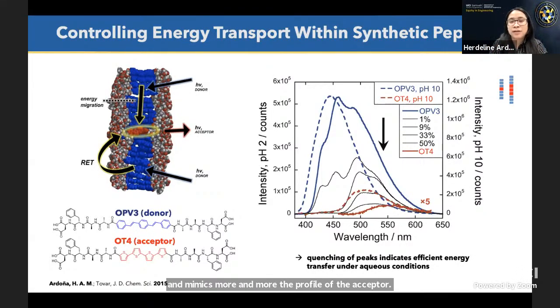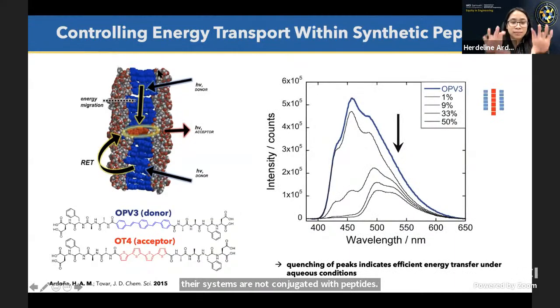What I want you to take away from this graph is that we were able to see this quenching of peaks, which represents a successful energy transfer even under completely aqueous environments, which usually does not happen easily when these electroactive systems are not conjugated with peptides. As a control, we looked at just assembling the donor stacks and acceptor stacks individually, and we can see that the quenching is not as efficient. So this tells us that we've been successful in combining the donor and acceptor units in one biological wire, and we were able to see and control the energy transport processes happening within our bio-inspired peptide-based nanostructures.